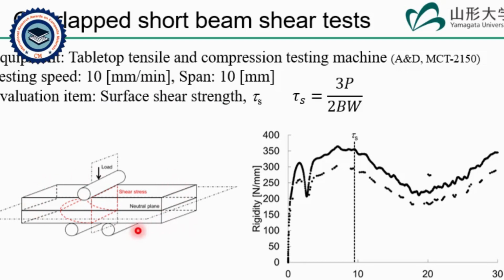Left figure shows a schematic diagram of the overlapped short beam shear test. For this method, specimens of the same type are overlapped and subjected to a 3-point bending test with a shorter span. The overlapping surface becomes the neutral plane of the entire specimen, resulting in zero bending stress and only shear stress.